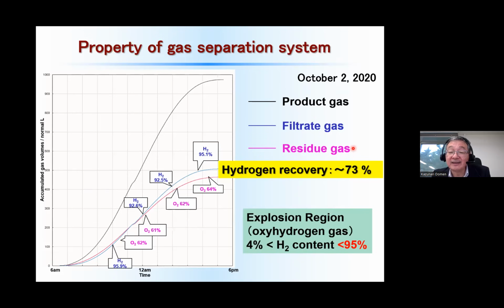More recently, we improved this system. We are now reacting the remaining oxygen using a palladium catalyst. So we can now get about 99.9% purity of hydrogen. The hydrogen recovery is now about 85%, and our target is a recovery of about 90%.